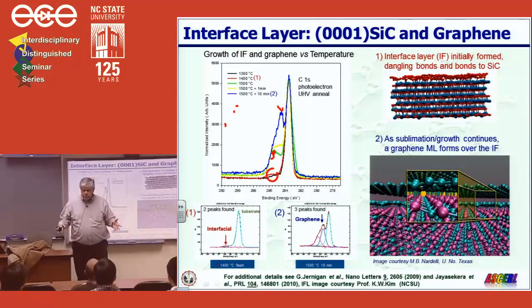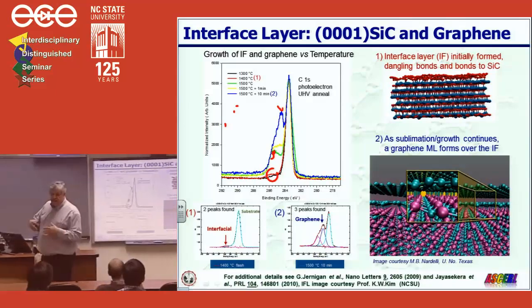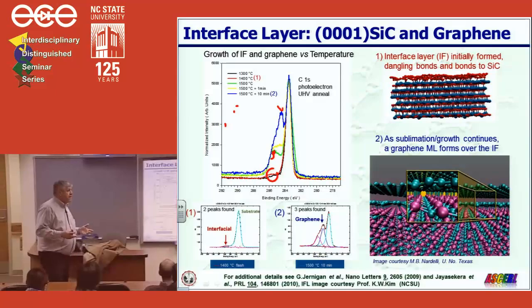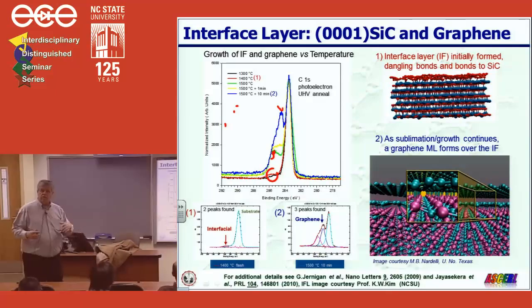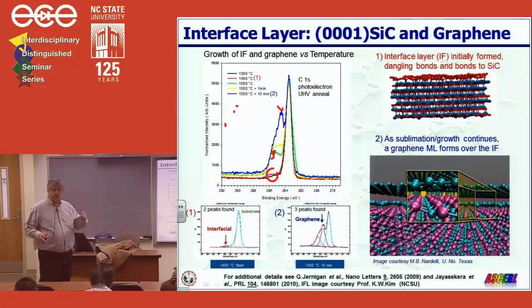And this blow-up shows this back bonding of about every 3rd carbon atom. So the structure on the silicon face has this interface layer, and the interface layer consists mainly of carbon atoms, which is still partially bonded to the silicon carbide substrate. On the carbon face, there's no interface layer at all.